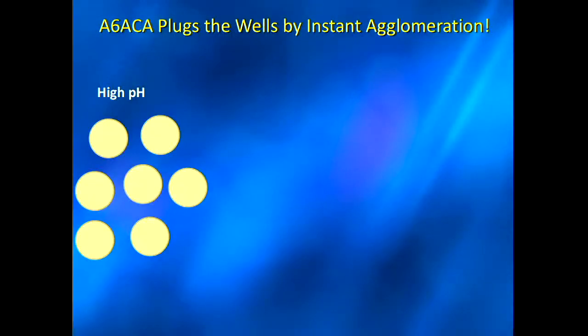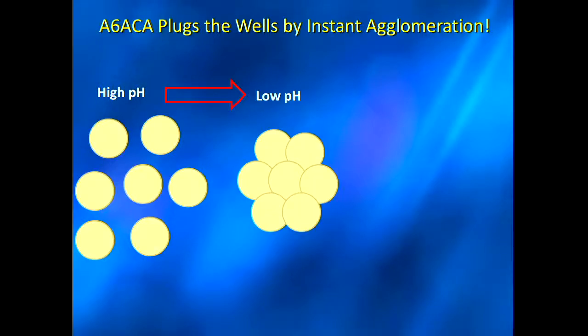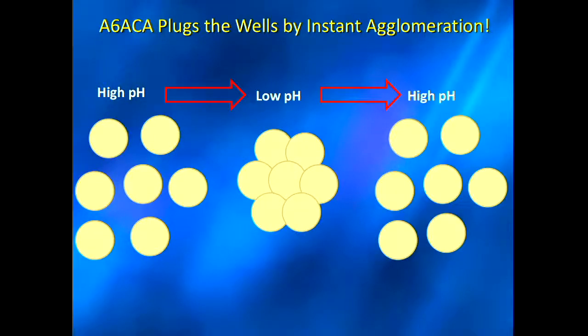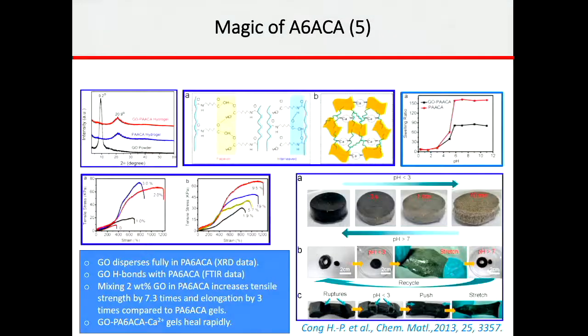And the way it worked is very simple. Because we saw high pH, they will be segregated. You lower the pH, they will be aggregated. You go to high pH, they will be again segregated. Okay? So what it means is that just by switching the pH, you put in a suspension, switch the pH, and it will do complete blocking. Okay? So that's another very interesting application.